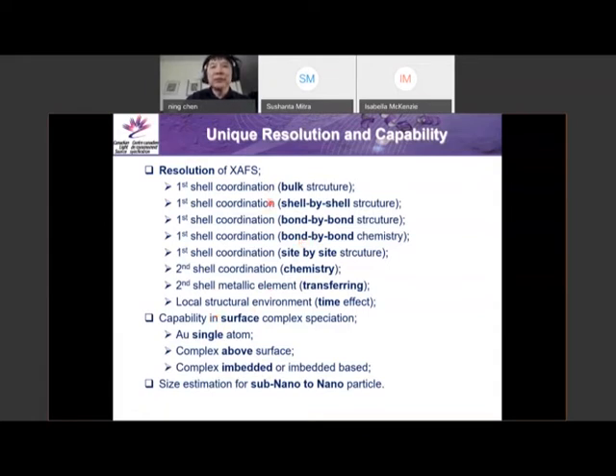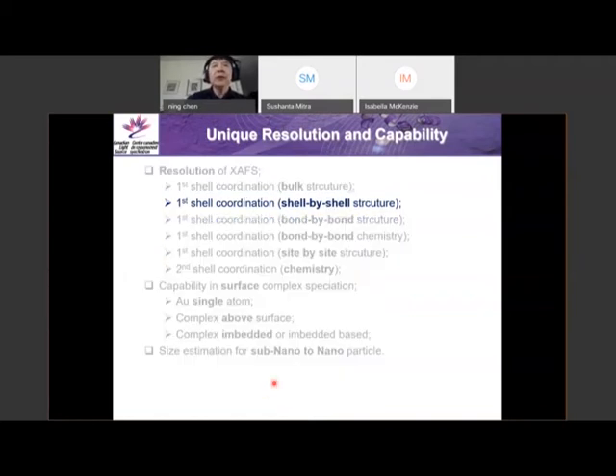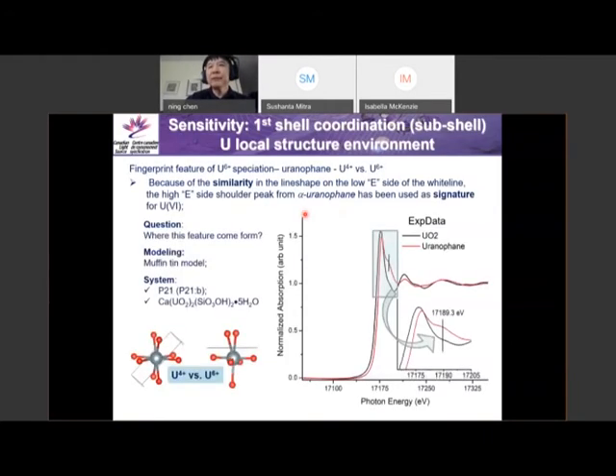Because of this resolution, we have capability on the surface, for example, single atom above the surface, or embedded in the surface. And then we can use that to estimate the size of nano to sub-nano particles. This is a gray zone or invisible for XRD if the size is sub-nano to nano scale. Okay, so I'm going to use one case to address shell by shell resolution. The environmental case is a very good case to address shell by shell resolution for the system.